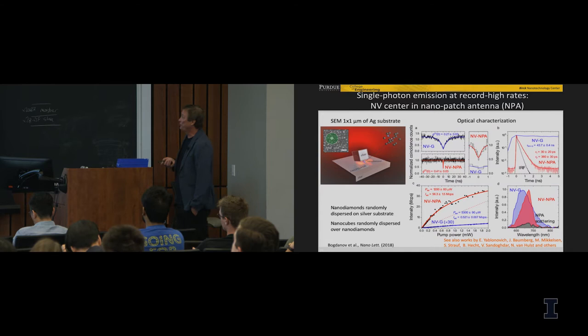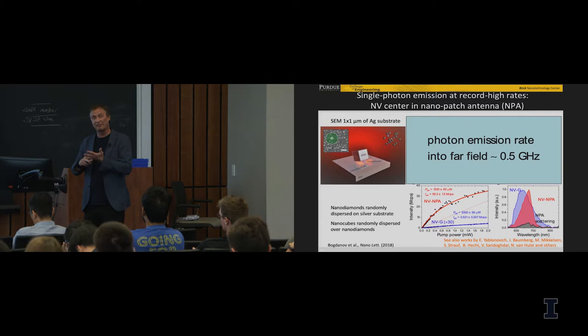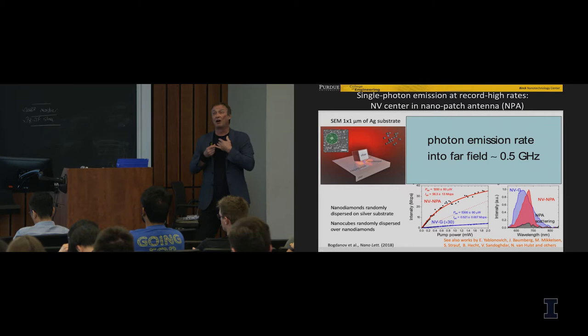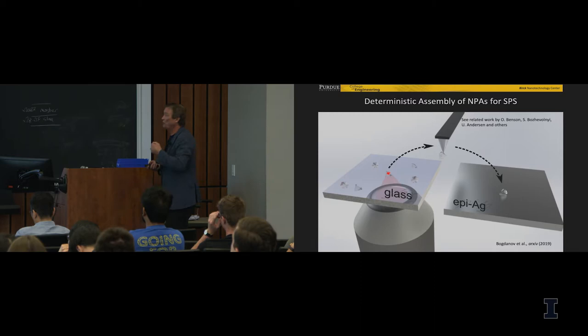And by the way, it's 30 million, but if you take into account that the collection efficiency of your detector is 70%, the angular collection is 50%, and the total transmittance for the whole optics we use is 25%, it means that actually we produce around half a billion photons per second at room temperature. So how to do it in a better way?